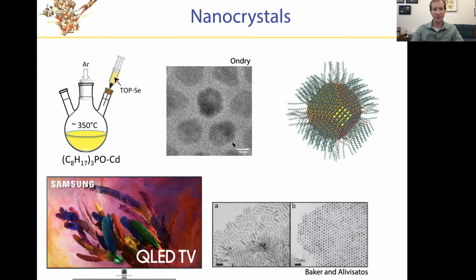Not only can we make little dots of these by altering the solution conditions and the protocol, we can make them in exotic shapes, for example, rods, as shown in this micrograph down at the bottom. And with suitable encouragement, you can even get those nanometer sized structures to further assemble themselves into larger scale ordered patterns. And panel B here are the very same nanorods, but now they're standing on end and packed in an ordered lattice. This is in essence a crystal of crystals and has yet again a different set of physical properties.